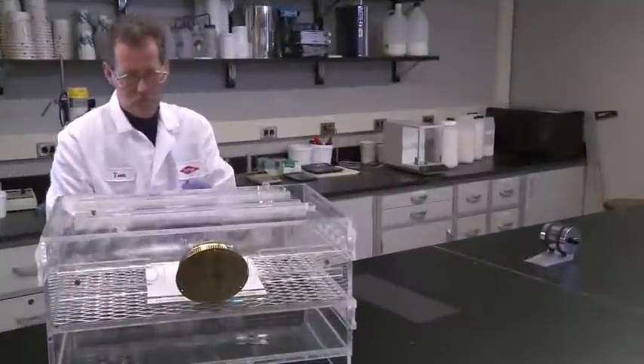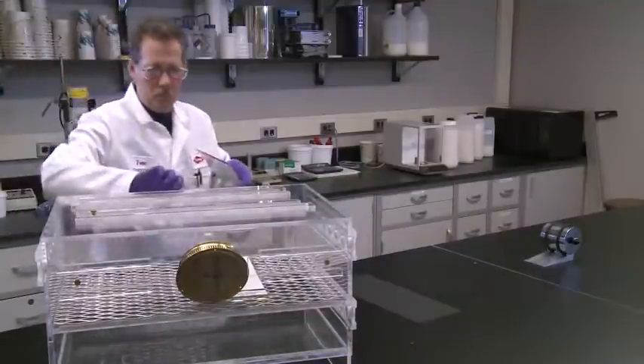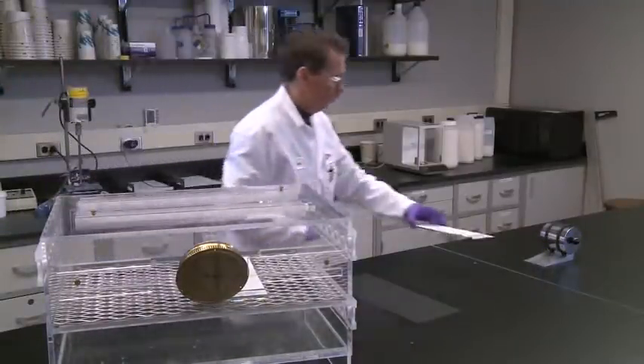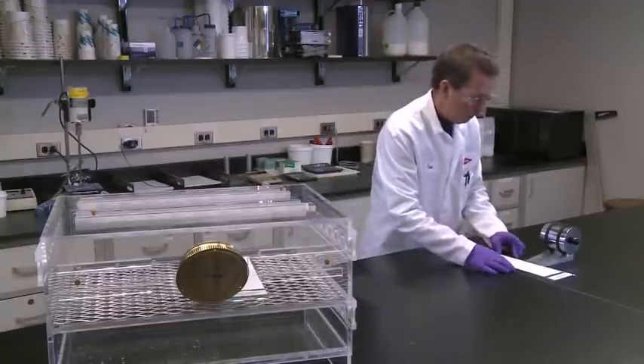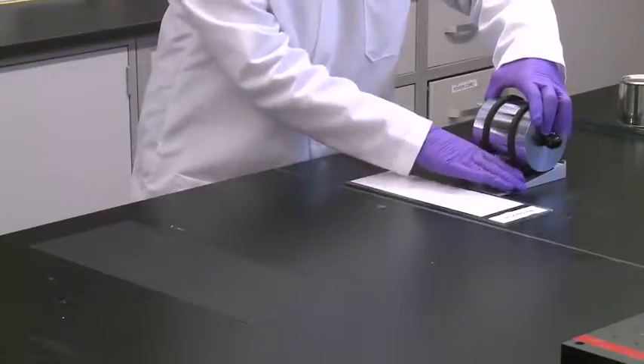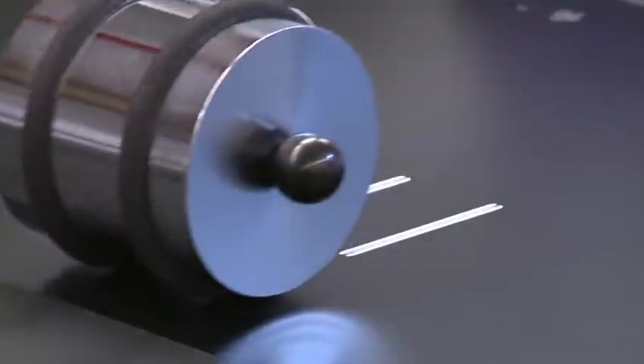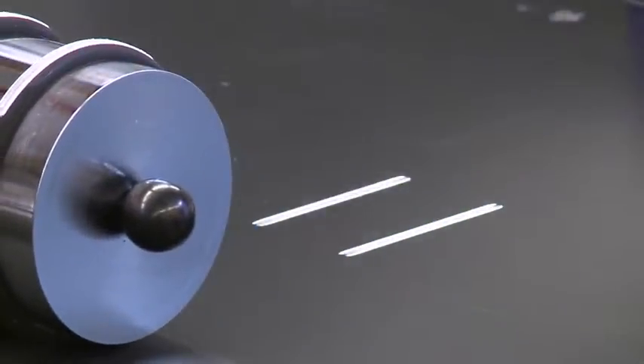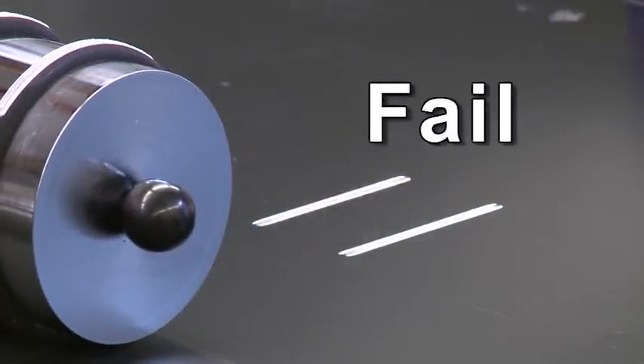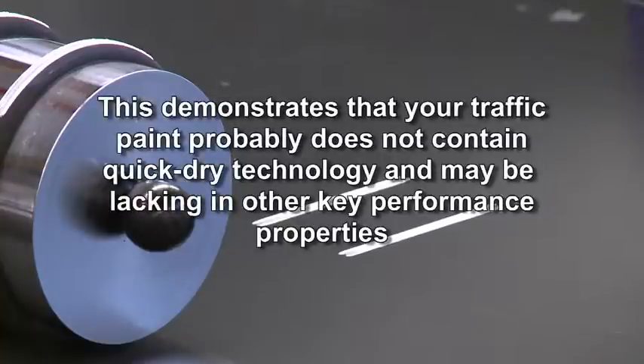At the prescribed maximum no pickup time in the specification, remove your test paint sample from the humidity chamber and place the glass plate against the ramp. Release the wheel so that it freely rolls down the ramp, across the paint film, and onto the black paper substrate. If the test paint has paint adhering to the rubber rings of the wheel or deposits paint onto the black substrate, as we see here, this is considered a fail. It demonstrates that your traffic paint probably does not contain quick dry technology, and it may be lacking in other key performance properties.